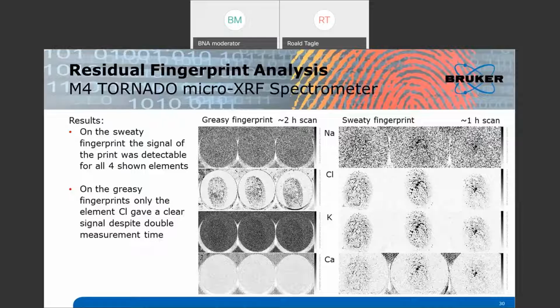And what we see here is very characteristic. The greasy fingerprint barely has any signal for sodium, potassium, or calcium, whereas there is some signal for chlorine that can be detected in the greasy fingerprints. And in the case of the sweaty fingerprint, we see signals for all four elements. So interestingly, chlorine seems to be, especially for the greasy part of the fingerprint, quite a good contrast element, as was presented or said before by Falk.